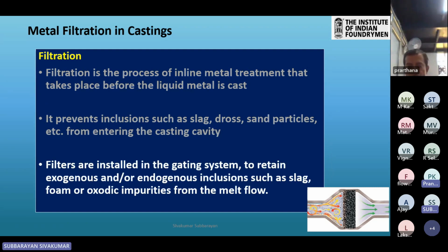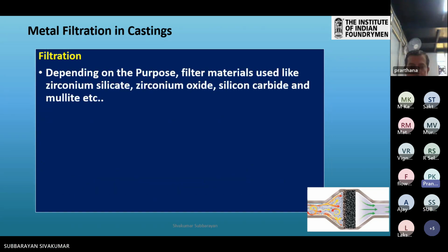So it is known that filters are installed in the gating system to retain exogenous and endogenous inclusions such as slag, foam, and other volatile materials which come from the melt flow. Depending on the purpose, filter materials used include zirconium silicate, zirconium oxide, silicon carbide, mullite, etc.